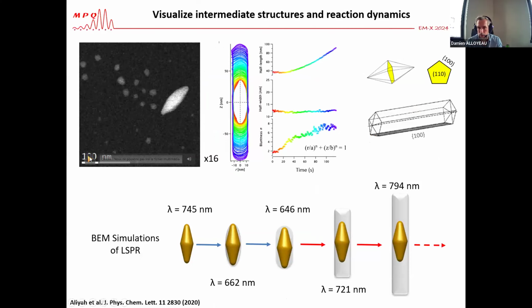Anyway, what you can see here in the contour plot of the nanoparticles is that first we observe the growth of anisotropic objects on the bipyramidal seeds. We also observe the growth of many spherical nanoparticles all around. So we were very happy. We have the same conclusion as with SAXS. And you see that, in fact, we have a transformation.